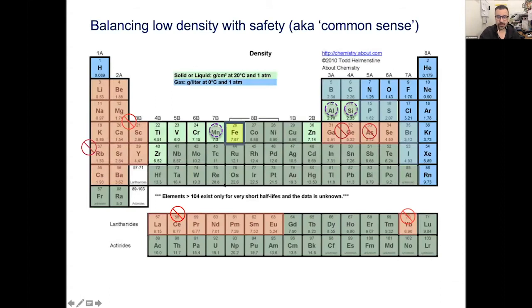But if you can get corrosion resistance by having, as we've seen before, multiple phases, a hodgepodge of elements and so forth, you may as well take this situation by the throat and try and make something that's quite or very lightweight and that actually just uses commodity, so non-passive, materials. So if you take iron, manganese, aluminium and silicon, basically things that you can find in a junkyard, from wheels, engine blocks and so forth, and then put them together, what actually happens?